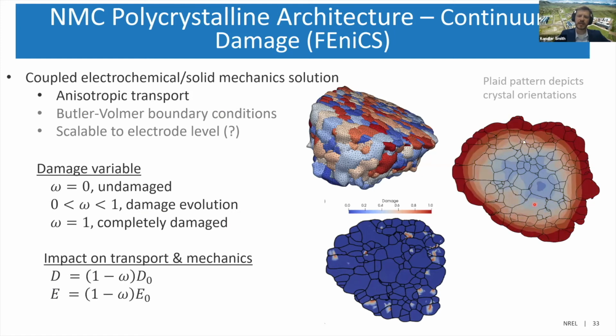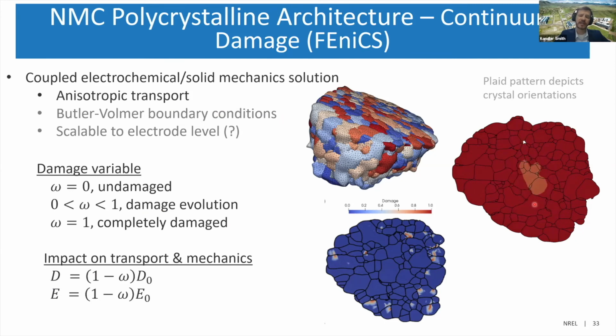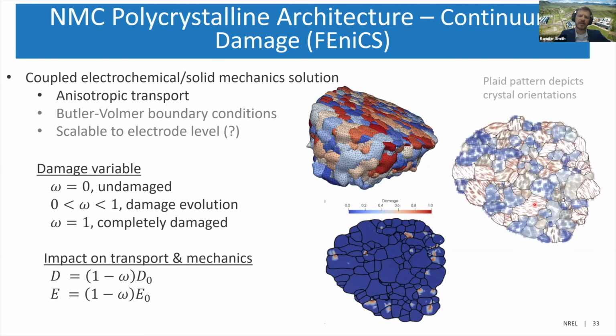So there's the concentration gradients in the particle. This is with uniform flux on the outside surface, so it's not quite the Butler-Volmer boundary conditions. And here you can see this plaid pattern depicts the different crystalline orientations of the individual grains. So where you see just a line, that means you're looking down the lattice, whereas when it's flat, you're seeing the face of the lattice.